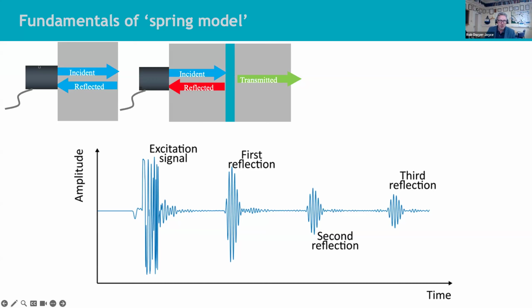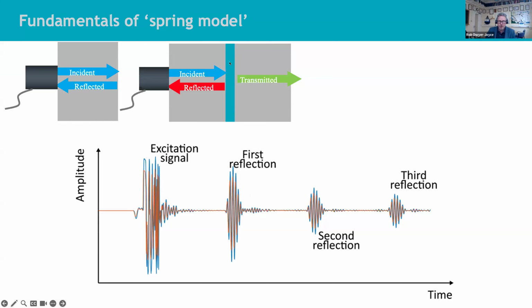This picture on the right-hand side is a reflection when there's no oil film present, just air. Everything reflects back, and you get a signal that looks a bit like this. You'd see an excitation pulse reflected from the sensor interface, a first reflection from the air interface, and then a second bounce as the wave came back and bounced again, first, second, third, and so on. Then if you put an oil film in the way, you get this red signal. Some of that ultrasound has passed through the oil film into the second bit of metal, and so you get a slightly lower signal. This first reflection, blue, when it was against air, we call the reference. Red, when it's against an oil film, we call the measurement signal.